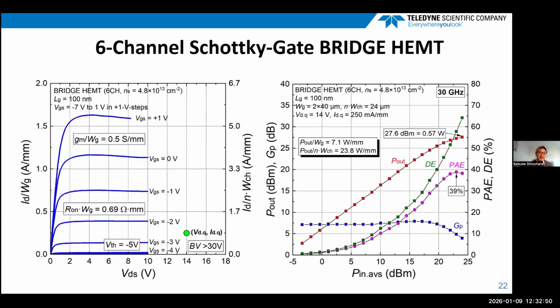So here I show the 6-channel Schottky gate bridge HEMT result. On the left, it shows the IV characteristics. And as you can see, this transistor behaves differently. Normally, the gm peak is obtained around 0.2 siemens per millimeter in the conventional AlGaN/GaN HEMT structure, while in the bridge HEMT, because the transistor operates like a MESFET, the gm keeps increasing with increasing drain current.